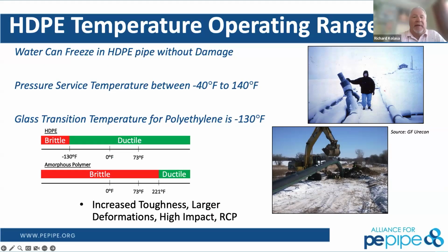Because we have this viscoelastic behavior of polyethylene, we are very ductile to very, very low temperatures. Not that you would ever operate in a glass transition area of minus 130, which is really unrealistic, but it's important to understand that you are ductile with high density polyethylene with the zeros and below zero type values. And that's really, really important. However, it does become contracted. So the amorphous areas do become tightened within the polymer itself. So this way, you still have that ductility, which is really, really important.